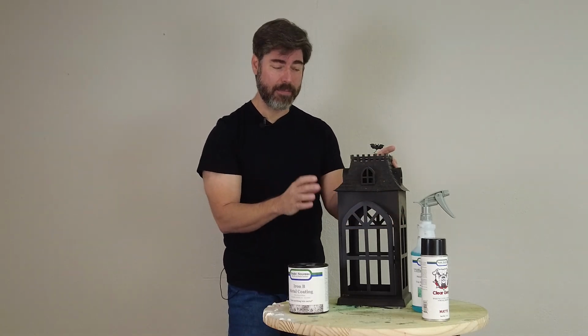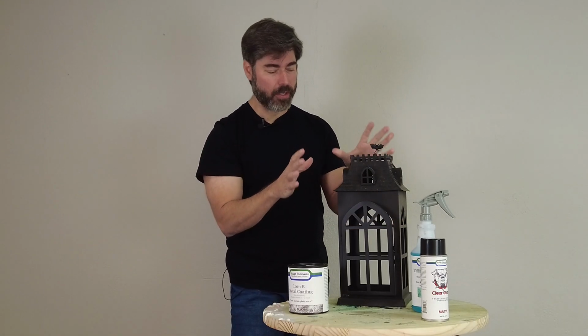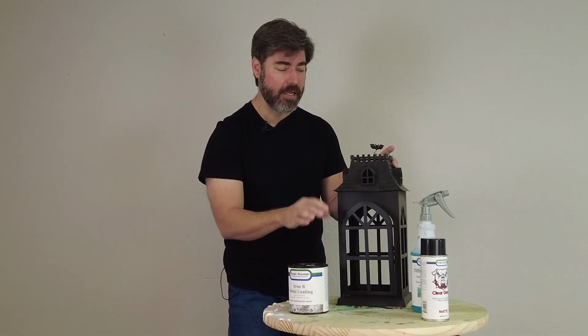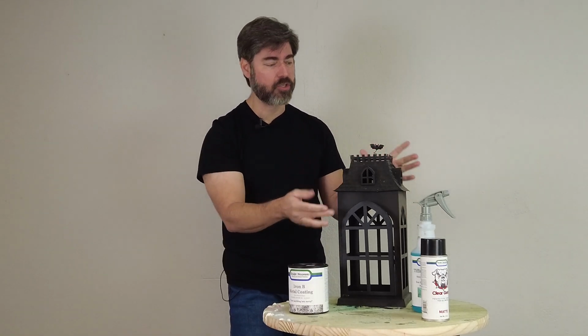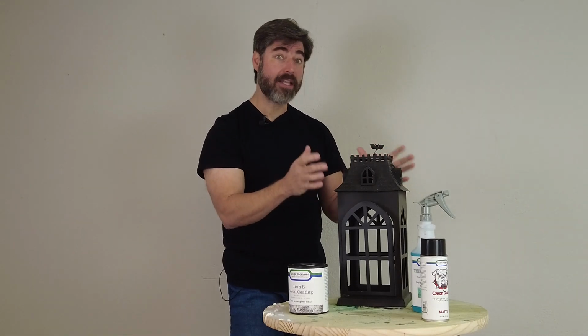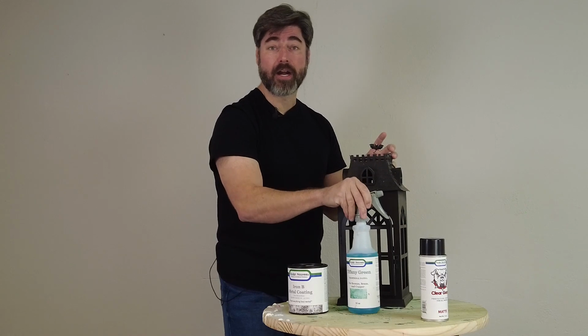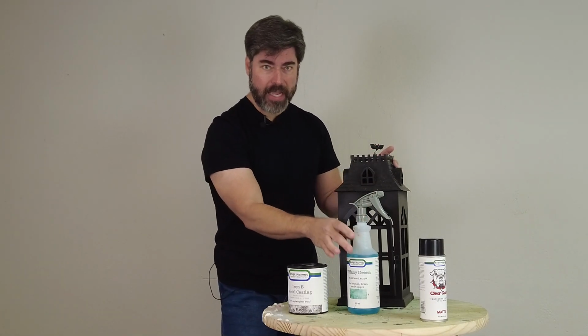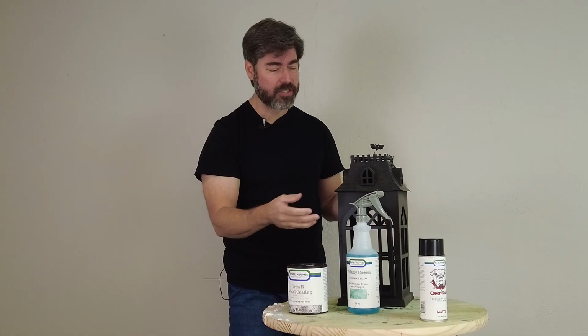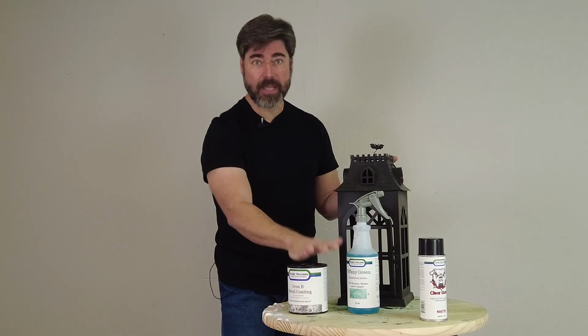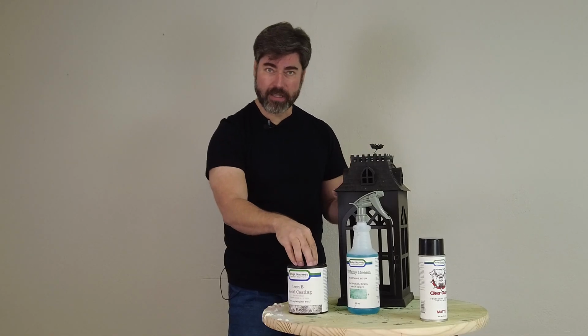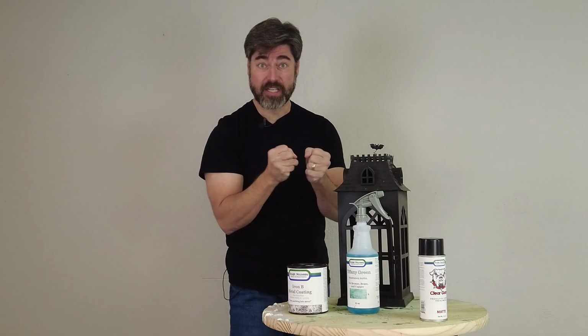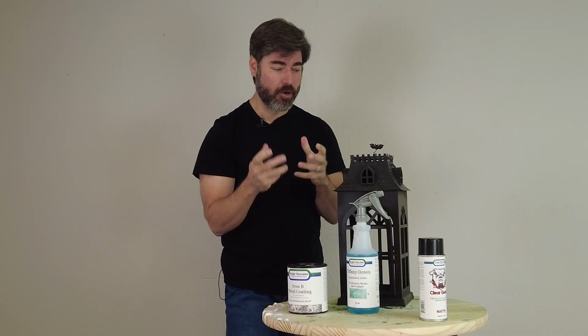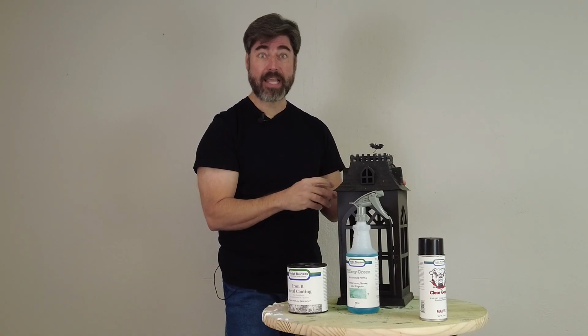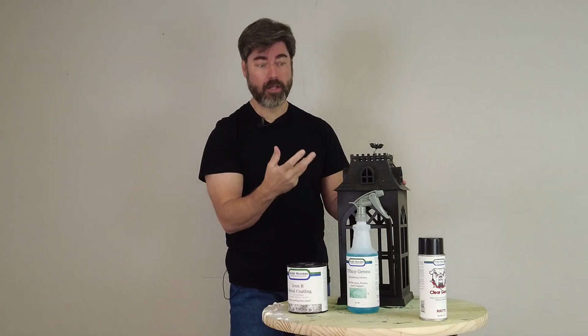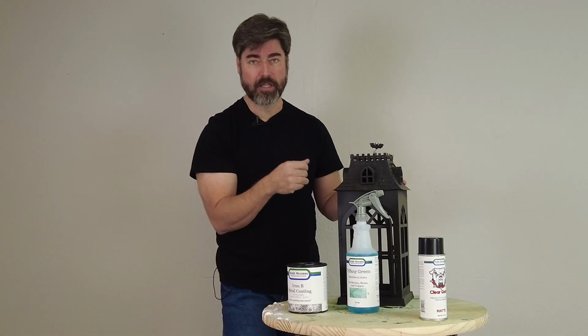And real important, the timing of this is what's really important here, is as soon as we put this Iron B all over our piece, or wherever we want the rust to appear, while it's wet, that's when we're going to apply our green patina. And this will react and oxidize to form real rust. But for that to happen, the Iron B has to be wet. When the acrylic in the Iron B starts to dry out and seal in those iron particles, you get little to no reaction. So real important to get that reaction started and well on its way before the acrylic starts to seal it off.